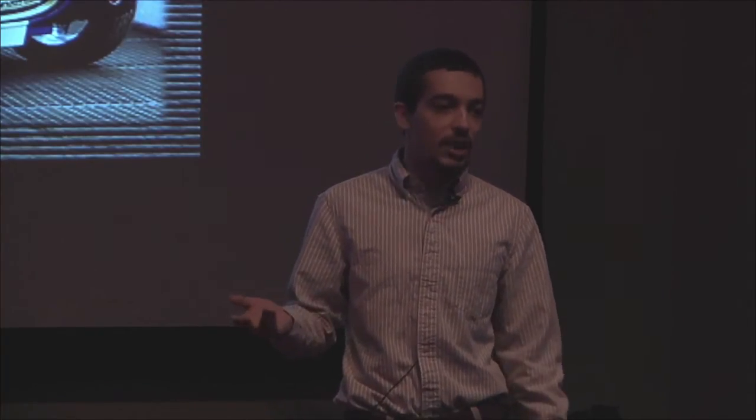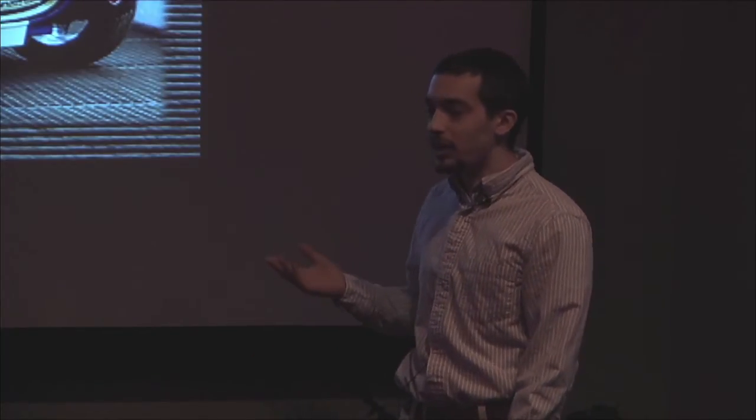We made it a little bit differently than how the Strati was made. The Strati was made as a giant solid piece and then the fenders were put on afterwards. Whereas the Cobra was made as an internal structure with shell pieces. Each of these shell pieces was then smoothed out and painted so that it could look how it does. This involves several new ideas in terms of how to actually smooth and paint these kinds of materials. Both the Strati and the Cobra are made using a carbon fiber reinforced ABS plastic — basically the same plastic that you make Legos out of, reinforced with carbon fiber to increase strength. It took just 6 weeks to go from designing the entire car to printing, assembly, finishing, and painting. It was demoed at the North American International Auto Show in Detroit this past January.